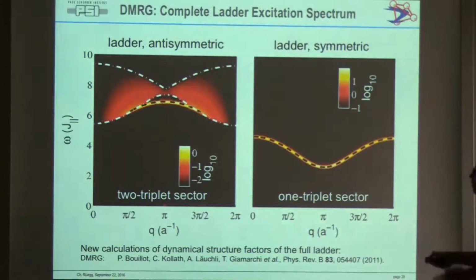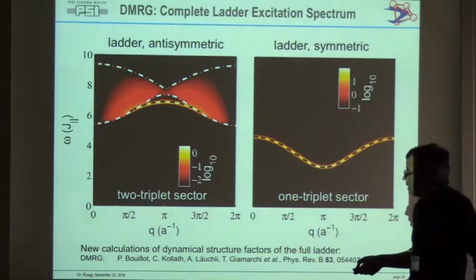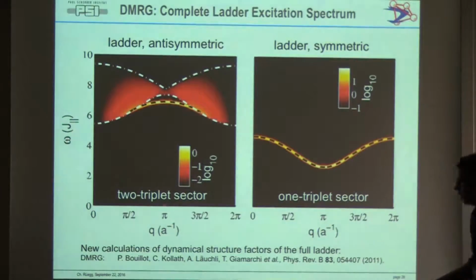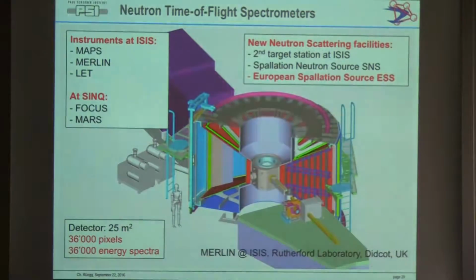So this is exactly what we can measure with neutrons. Neutrons have a selection rule, delta S equals 1, but you can choose all the Q values you want. So this is very powerful, and we want to measure exactly this in an experiment. The calculations you see here are DMRG calculations done in the group of Thierry Giamarchi and Corinna Kollath at that time in Geneva. So we use modern spectrometers.